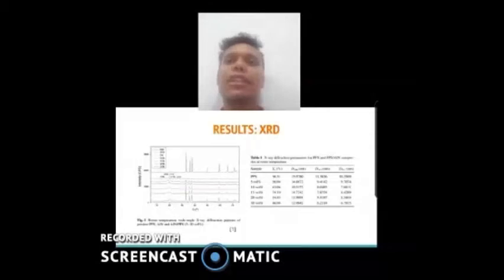An X-ray diffraction experiment was carried out at room temperature to investigate the effect of the aluminum nitride addition on the crystal property of the matrix. For the PPS, the most intensive diffraction peak appeared at 20 degrees. The composites displayed similar diffraction patterns to those of the neat polymer, although weaker and wider peaks indicate less structural order. The degree of crystallinity was estimated from the approximate relative areas under the amorphous and crystalline bits of the diffractograph, as collected in Table 1. The maximum value was 74% with the 50% aluminum nitride PPS composite.